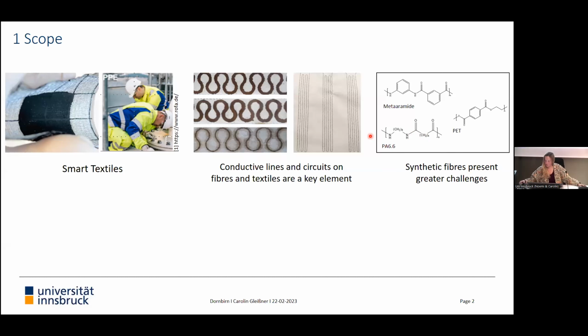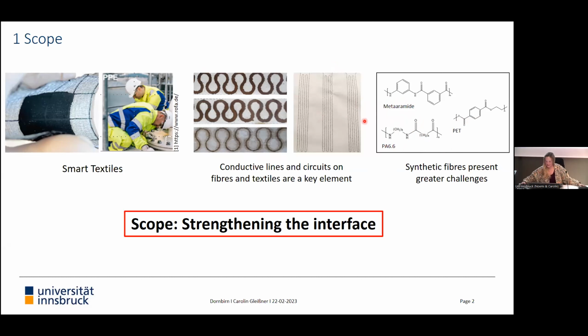But compared to natural fibers, they have a disadvantage because they often have smooth surfaces. They have low surface roughnesses. Also, compared to cellulose, there is rather a lack of functional groups. So therefore, if you want to create a composite, you often face interface stability problems. And so the goal of my work is to strengthen these interfaces between the metal and the fabric, for instance to improve the abrasion resistance and the washing fastness.